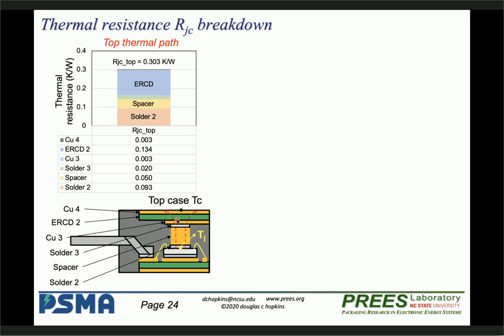So in the simulation, I only applied the heat transfer coefficient on the top surface, top case here. Because I need all the heat to go upward, and then I will capture the temperature difference between junction to top case. Then I can calculate the thermal resistance, RJC top. And in addition, we can use the same concept to extract each layer thermal resistance. So here's a breakdown.